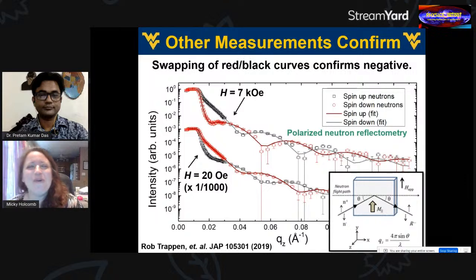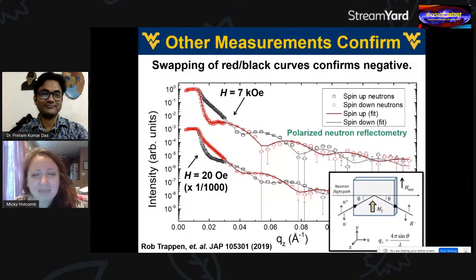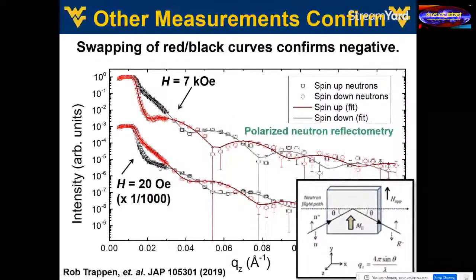Just for thoroughness, we also did some neutron scattering measurements, and these are complicated measurements to be able to explain, but the thing that is obvious is between this set of curves on the top, you see the black one is on the top here and the red's on the bottom, you see they switch in this other case. So, regardless of all of these weird humps and the fitting that has to go on, the fact that they switch tells you that the magnetization reverses. If you're curious about it, there's a paper link down here that you can take a look at. So here are various different measurements telling us that we have this magnetism switching.